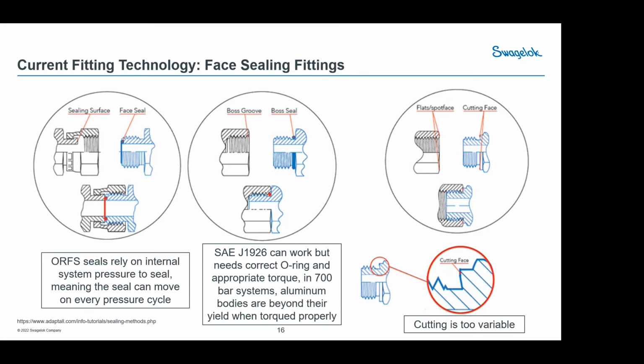The other way that this thing can come loose is that people have a tendency to want to lube up these threads. If you put a bunch of lubrication on it that's very slippery, you change the friction coefficient on the threads, and that allows it to not maintain the same load onto the shoulder and then work its way off. So care needs to be taken there. If you see problems with O-rings coming out, it's not the O-ring, it's the body coming apart, and you need to look at your design to make sure your characteristics are proper for that. But as a general rule, if it's done right, they can work fairly well, and they work well over time. And that's a good option for being able to do things like gauges and transducers.